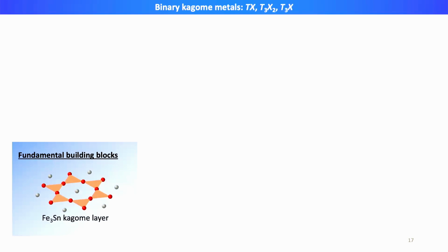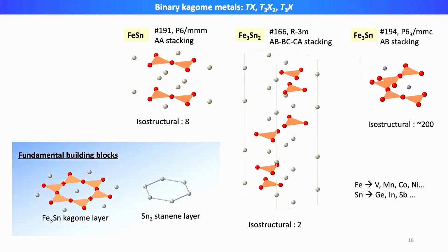And the second element needs to be electronically different enough from the first element that's forming the kagome lattice itself, so that we can treat their electronic states separately. So here you can see an example of such a kagome structure that's composed of transition elements forming the kagome lattice itself, while the tin, which is a p group element and is very different from iron, is taking the void space. So with this as the building block, together with another motif that's the honeycomb structure of the second element, this is the binary compound we could identify that would host this kagome lattice in its crystalline structure.